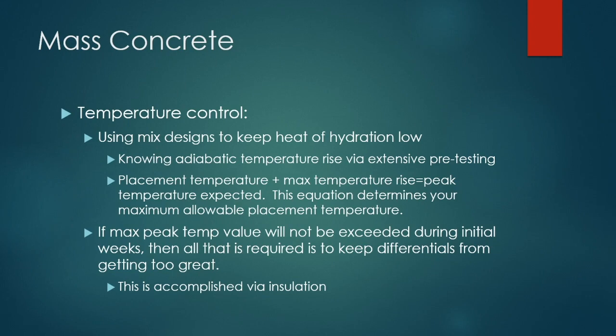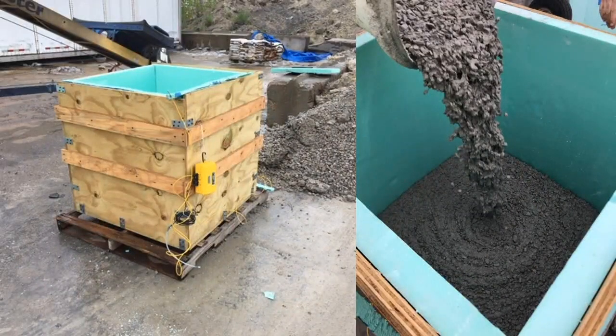And here's an example of some of this extensive pre-testing that gets done very often. Here's an example of an insulated cure box. It's about a 1 meter by 1 meter cube, or one cubic meter. And what we do is we place sensors in a variety of locations inside this mass and monitor them. If you see right here where my mouse is, there's one of our recording devices, and we've got all these sensors that are ready to go down inside this concrete.